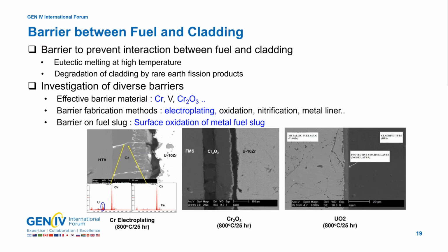And as I said before, because of the metal fuel and metal cladding, chemical interaction can occur. So we investigated barriers to prevent this chemical reaction. The barrier functions as a diffusion barrier of the elements. So we tried diverse barrier candidates, and good behavior was found for these barriers: chrome, vanadium, and chrome oxide. The chrome can be electroplated on the inside surface of the cladding, and the chrome oxide can form by oxidation of the inside of the cladding.